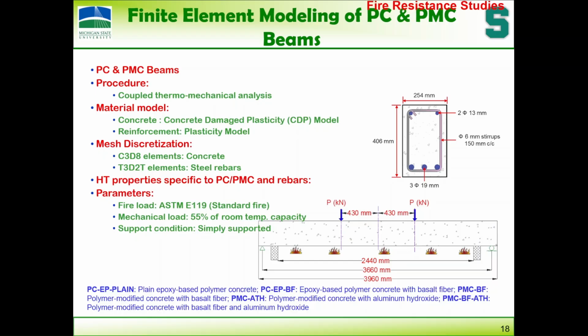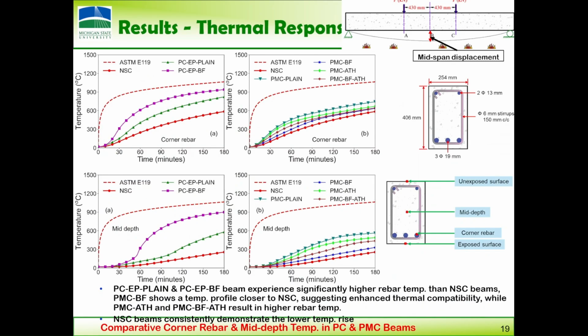We did the same thing with the same model, except we brought in the performance problems of polymer concrete and polymer modified concrete through material models. And then we analyzed very similar beams. Look at two things. Here, the temperature in the corner of the polymer concrete beam: can you see here, you reach that 600. Remember, in normal concrete it was not reaching that at 3 hours. At 30 minutes itself, you have about 400. In less than 60 minutes, you will have nearly 600 degrees in polymer concrete because of the high thermal conductivity of these materials. Polymer modified concrete is better.